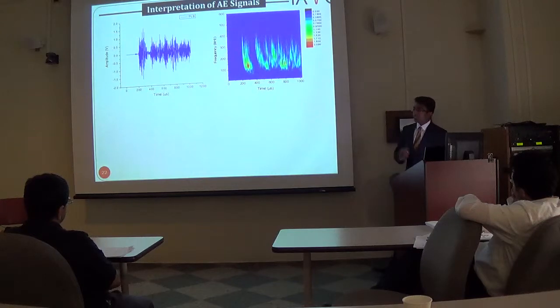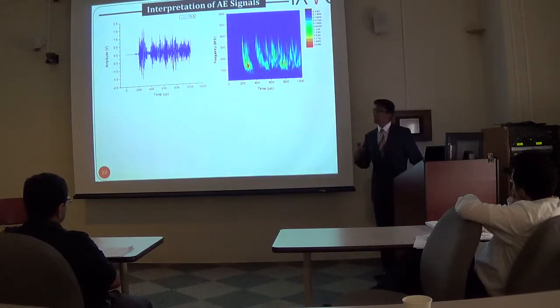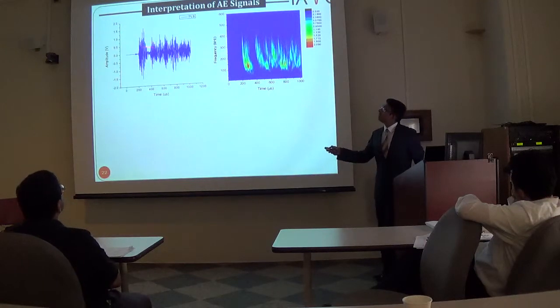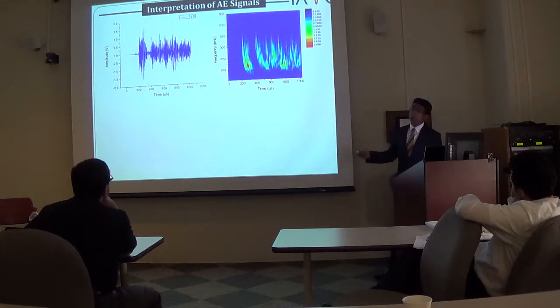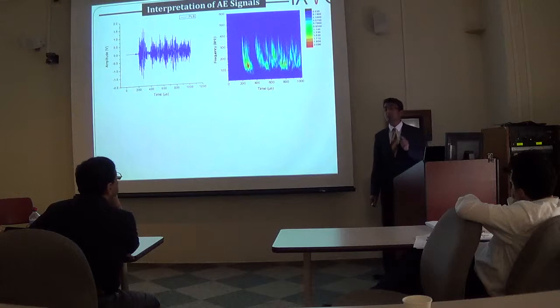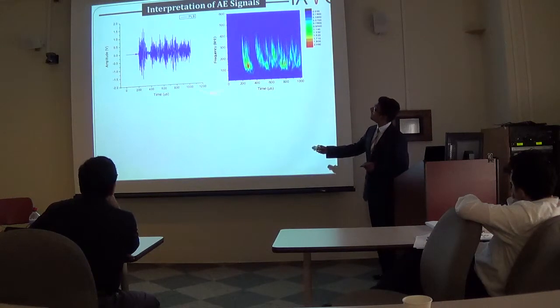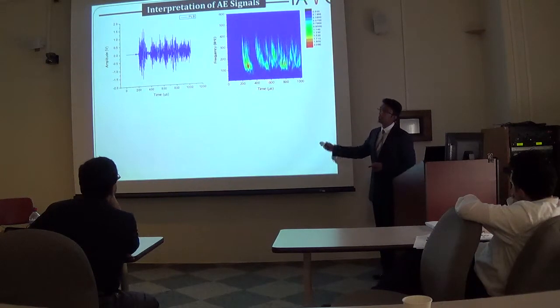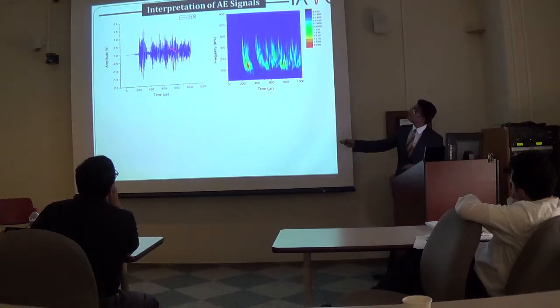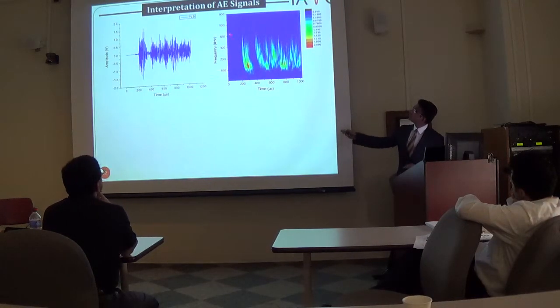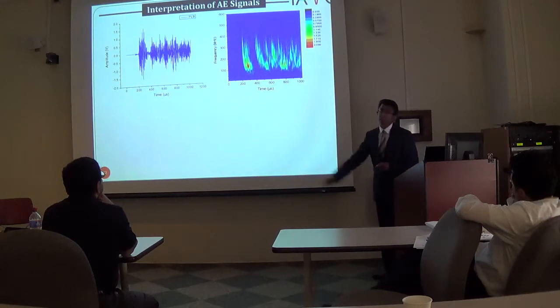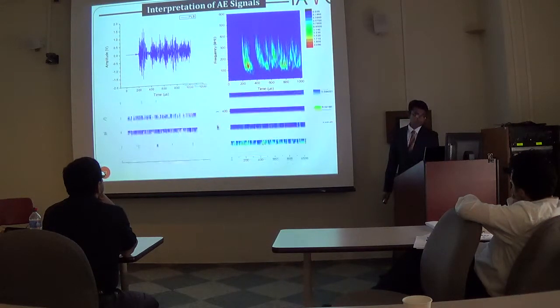Now, in order to understand if the advanced frequency analysis and the features could be utilized to separate the four sources, the waveforms were converted into the frequency domain, and the frequency evolution of the waveforms was also studied using wavelet analysis as shown here. So you can see that the initial packet of the waveform was associated with a high frequency, but as it propagates, we start to see these low frequency phenomena.